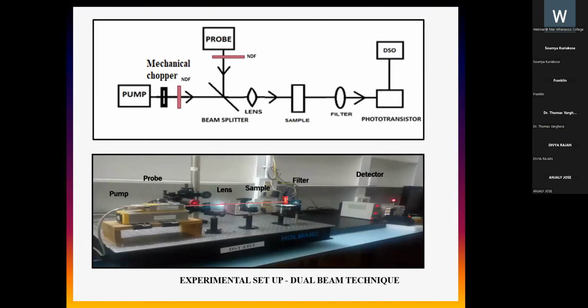This is the block diagram of the thermal lens setup, and the figure below is the setup which we have used in our lab. We have used a dual beam pump probe mode match technique for this experiment. That is, the generation and detection of thermal lenses is achieved separately by the pump and the probe. In the mode match technique, both the beams are focused by the same lens so that the radii of the pump and probe beams are similar within the sample.